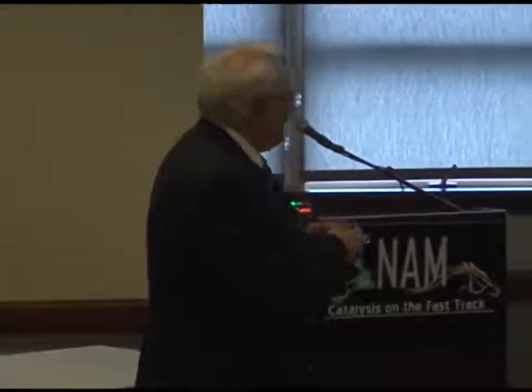And Jim Haw's group did the NMR spectroscopy, magic angle spinning NMR, and they found going down from a high temperature or up from a low temperature, the resonance broadened to the point of being undetectable at a particular temperature. And that shows a balancing off of two effects mentioned up there, which is evidence of the dynamic uniformity of the sample.